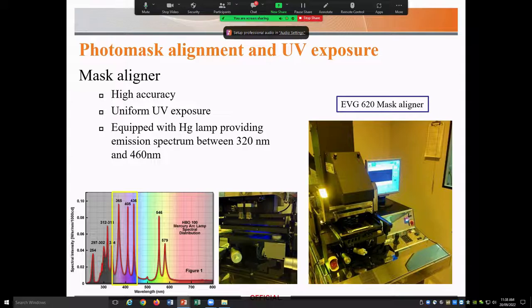The spectral sensitivity of the photoresist should match the exposure tool we are using. Here at ANFF-SA, an EVG 620 mask aligner is used to perform this step. It is equipped with a mercury lamp providing an emission spectrum between 320 nanometer and 460 nanometer, which covers a wide range of photoresist. The exposure time depends on the exposure dose, of course, the intensity of the lamp, and the thickness and type of the resist.